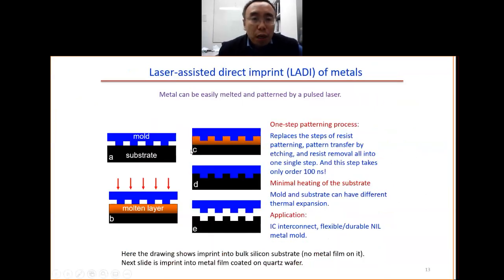In this example here, we can do the imprint into the metal using laser pulses. We know that it's hard to melt the metal, you need a very high temperature, but it can be easily melted by using a laser pulse. The example here shows the imprint into bulk silicon. This is not metal, it's silicon, but we can do the same thing on the metal.